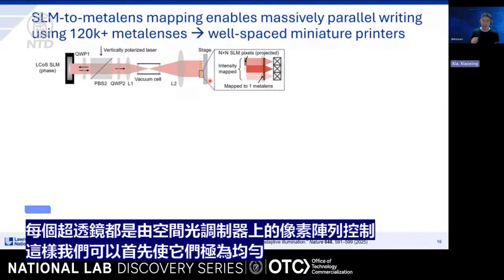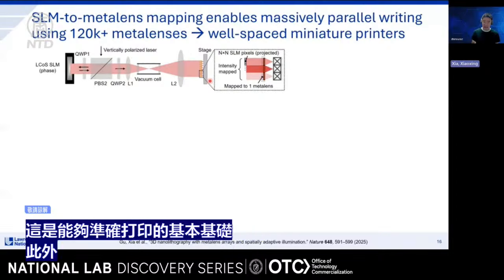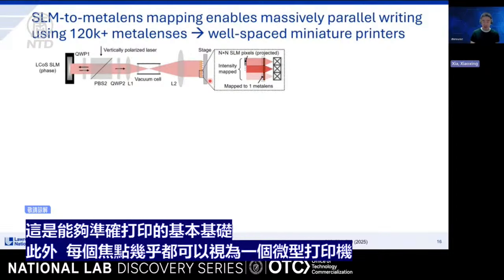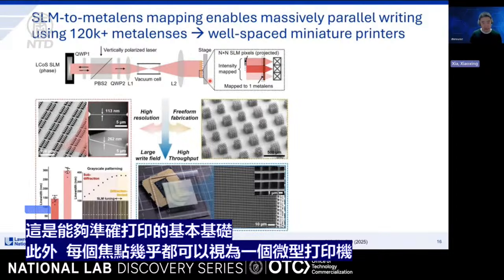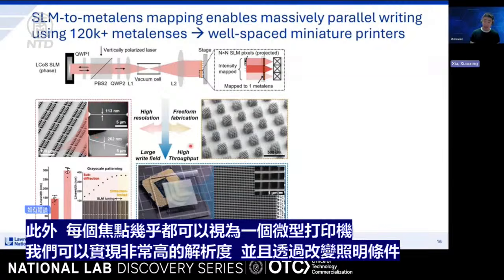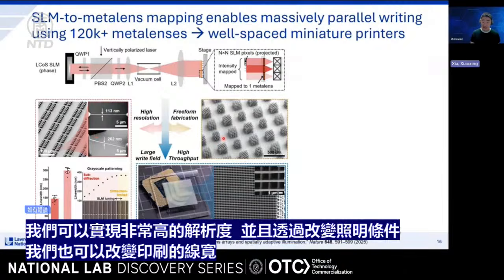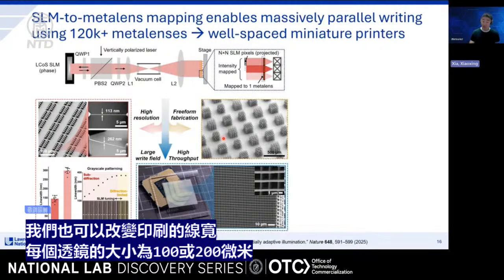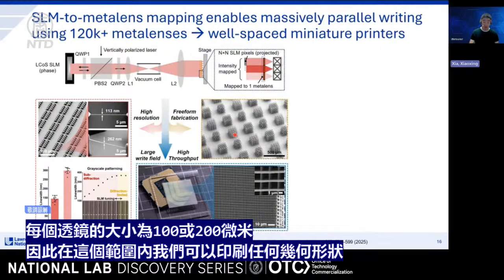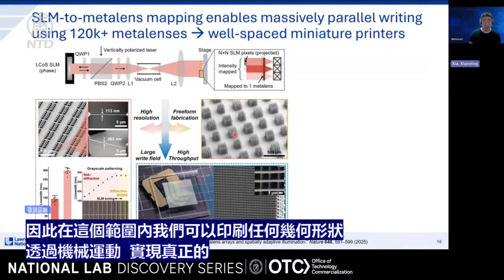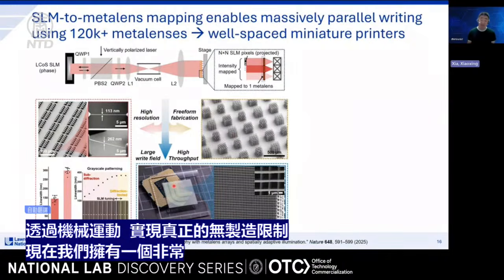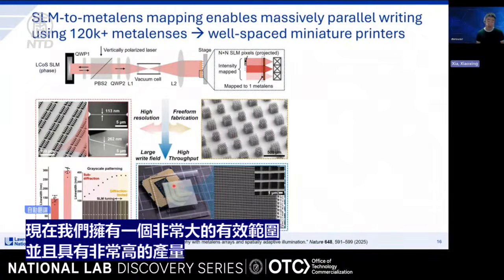On top of that, each focal spot pretty much acts as a miniature printer in itself. So we can really have very high resolution, and by changing the illumination condition, we can also change the line width of our printing. And each lens is either 100 or 200 microns in size. So within that size, we can print any geometry through mechanical motion. So really freeform fabrication. And all together, we have a very large write field with very high throughput.